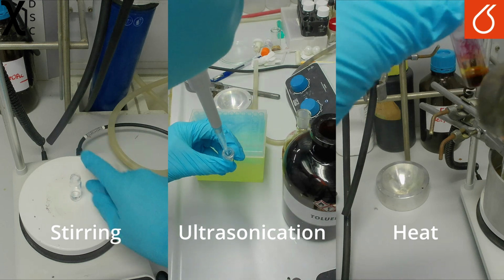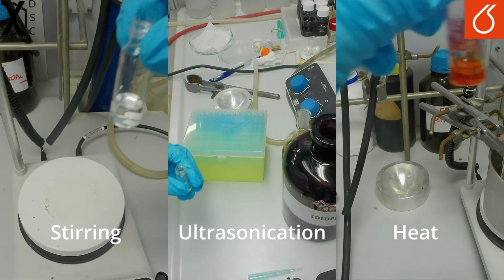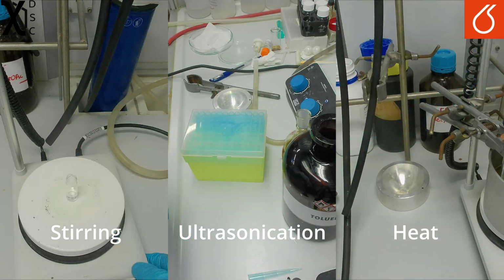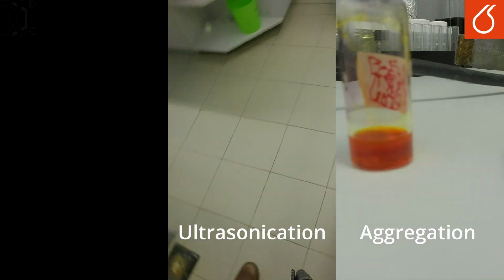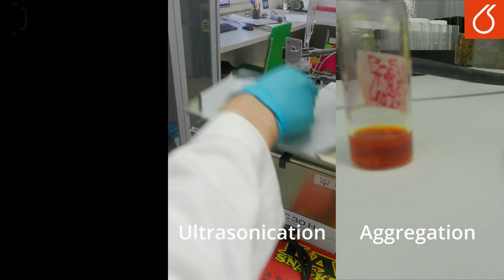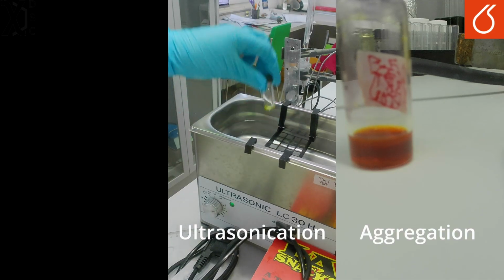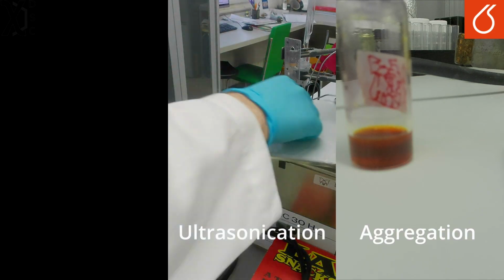Caution should be maintained with heating, however, as a supersaturated solution can form, which when cooled down again can rapidly form aggregates, making a suspension, or entirely precipitate a compound. With polymers, this is more complicated, as gels may form prior to precipitation. P3HT is shown here, which it is claimed can form beneficial aggregates. The paper is linked below. Regardless, precipitation, aggregation, and gels can affect the films formed, and so caution should be maintained about cloudy solutions. Once we have a compound in solution, we can start depositing the films.